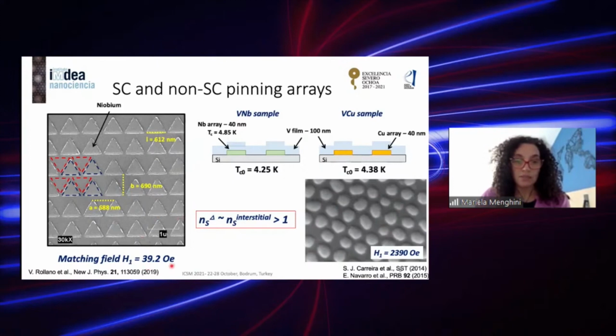One is the matching field, in this case 39 Oe, so that's the field, as you know, where we have one vortex per triangle, in this case, per pinning site. The dimensions are such that this saturation number, so the number of vortices that can be allocated in principle in the triangles, is larger than 1 and actually is similar to the interstitial saturation number. So the triangles are indicated here with these blue lines, and if you look at the interstitial lattice that is formed, it is these down red triangles, right, that have similar size as